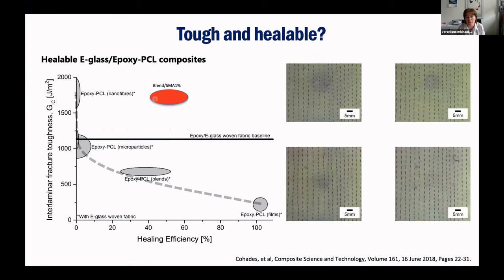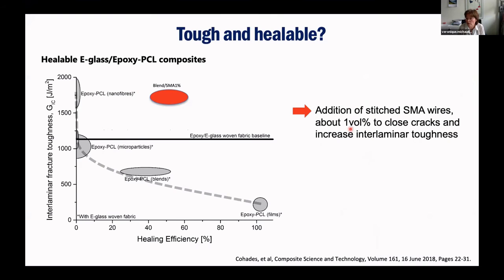And we saw that indeed, in that case, you have a good toughness because the toughness is given by the SMA stitches that you have, and you also have a decent healing efficiency. And we also published this one, and that was in 2018. So what we see here, it's blocked. So 1 volume %, so it's not so much, and it can make sense.